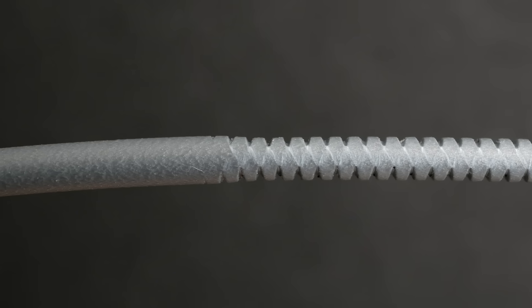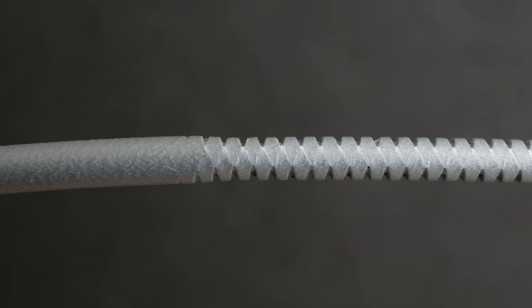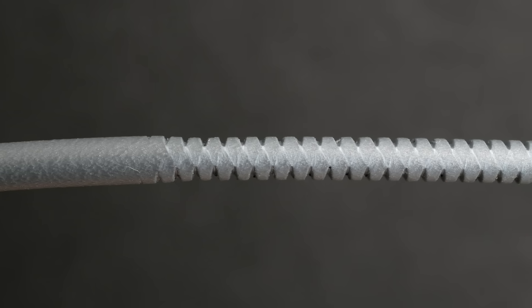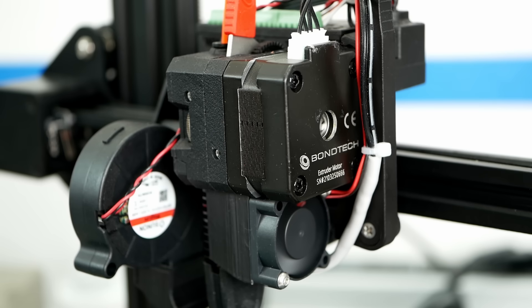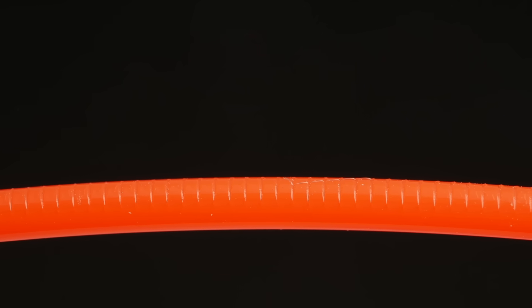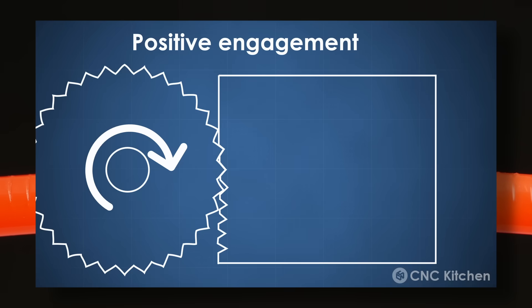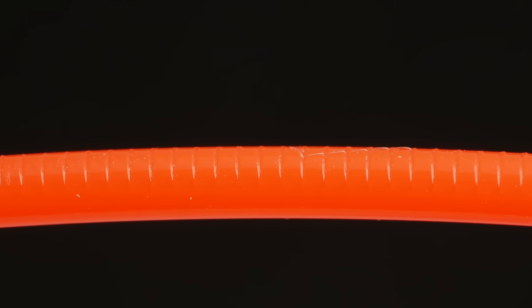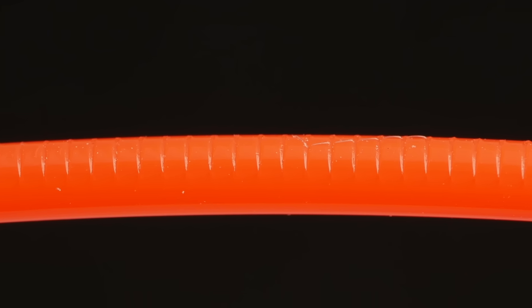On the other hand, the filament literally gets crushed if you apply too much pressure. This doesn't only deform the material and makes it harder to feed. Crushing, so permanent plastic deformation takes a lot of the motor's energy and you therefore lose power to convey material forward. Additionally, you'll create more friction in the bearings and might even break your idler arm if the pre-tension is too high.